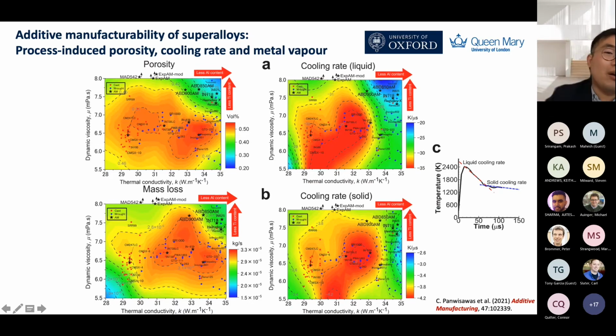So we benchmark on that, and then we generate what's called a thermal fluid map to say something about manufacturability using porosity and cooling rate in the liquid state. As is shown here, from the liquid to solid, there are some different cooling rates, as you may notice in your measurement if you do some in-situ thermal imaging, thermal monitoring, you will see that this actually happened. And more importantly, from the high fidelity model, we can generate something called a mass loss map